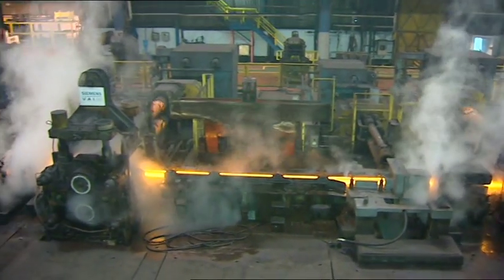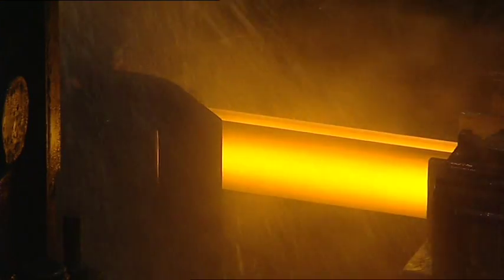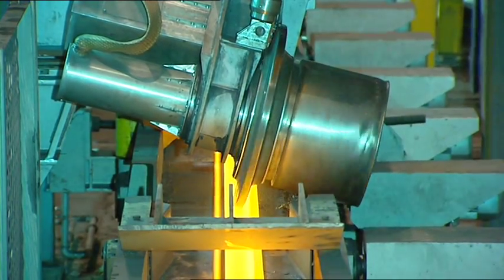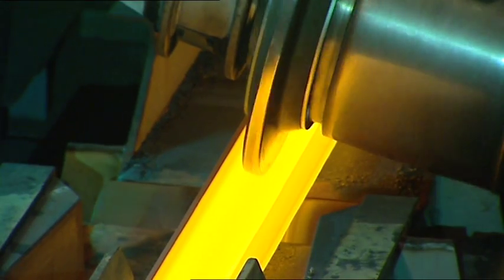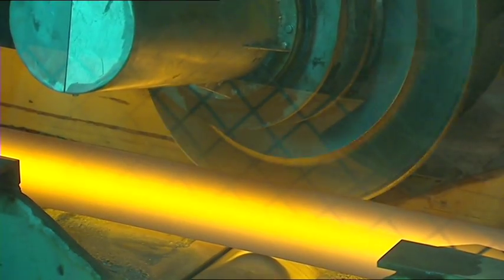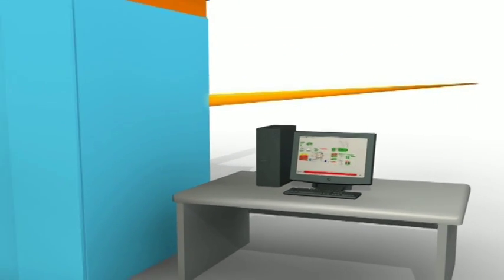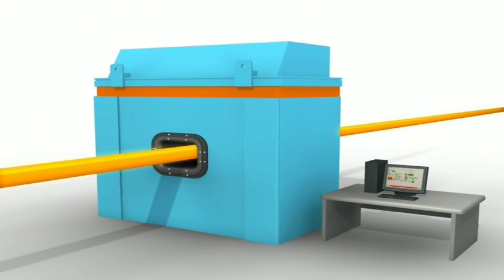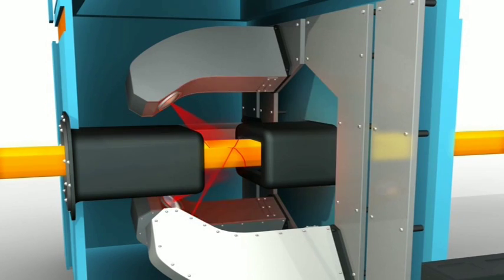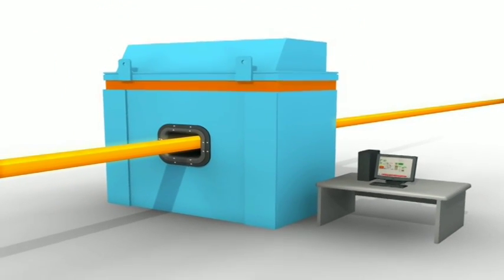The substantial capacity, flexibility and process consistency offered by our rolling mills enables us to achieve the full range of international specifications. In order to retain traceability, the rail is stamped with a unique identifying mark, showing the cast, strand and rail identification number every 5 metres, ensuring every length is fully traceable. A hot dimension inspection system scans every rail along its full length and records all of the rail dimensional information. This allows a team to align the key dimensions to the nominal profile and ensures that all rail is rolled to the specified requirements.